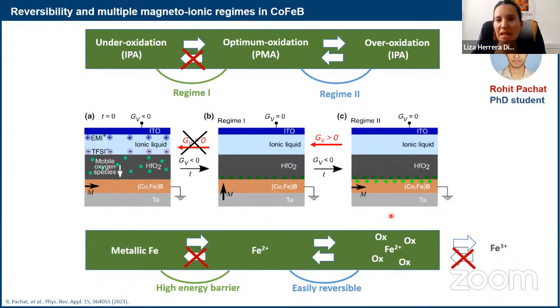One other thing that makes us think that this is the case is that we know that if we overdo the oxidation on this state, which is already in plane, and we keep going with the oxygen, at some point it will not be reversible anymore. And this is where we think that we actually go to iron 3. So it's a similar situation as here: a higher energy barrier, you cannot go back. This is really our interpretation right now.